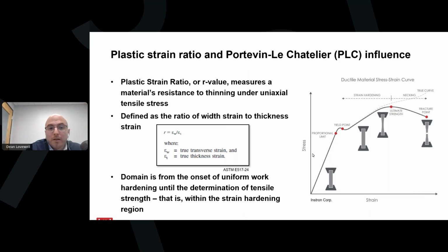During tooling design, the R value along with the finished geometry will both be considered for how much work can be done without risk of excessive thinning. For this reason, it's important that the plastic strain ratio falls within a defined window. Non-conforming material, of course, risks being overworked, which can lead to cracking, or underworked, which would result in insufficient work being done to develop the strength desired.